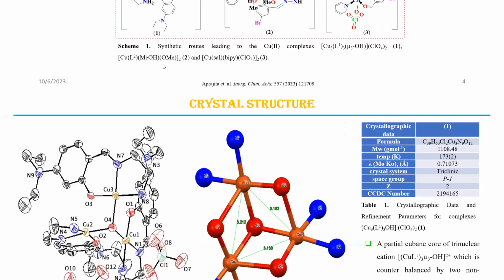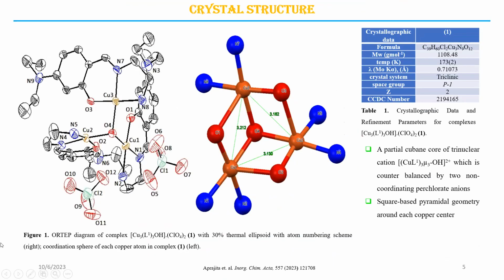We have obtained the crystal structures of all three complexes. Figure 1 shows the ORTEP diagram of the first, trinuclear complex. A partial cubane core of the trinuclear cation was formed, with two types of bridging: one with the phenoxy groups, and the second with a centrally placed hydroxy ion which bridges the three copper ions. Using the Addison parameter, we found the geometry around each copper atom is square-based pyramidal. The axial copper-oxygen bond was longer than the equatorial bond, showing a Jahn-Teller distortion.